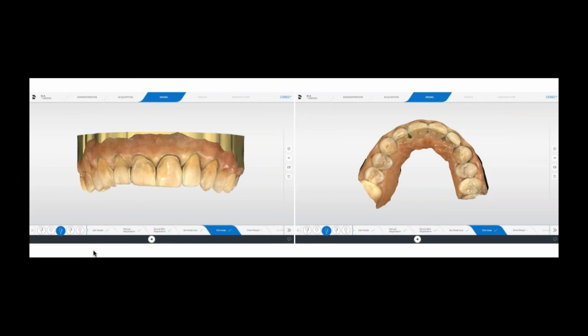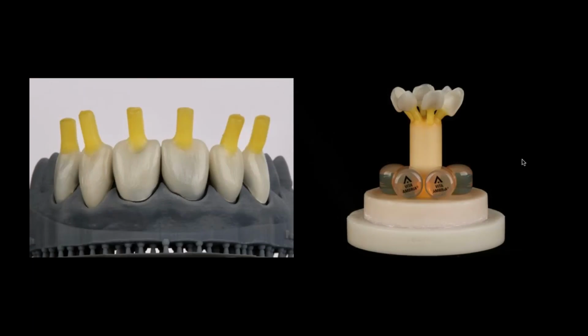Once we scan this, I like to sometimes leave the 000 retraction cord, remove the second cord, dry, and scan very well. You can see here on the palatal aspect, the 000 cord. Just make sure that you don't have this excess of cord very long and going all around. That will affect your scan. But we can scan perfectly, leaving the 000 cord placed in the sulcus. Just make sure that it's not on top of your margin. And then I send this to Telmo, and Telmo started to design the restorations.